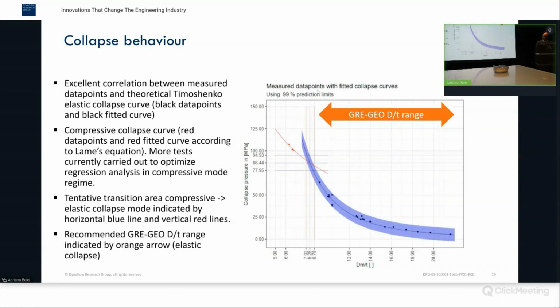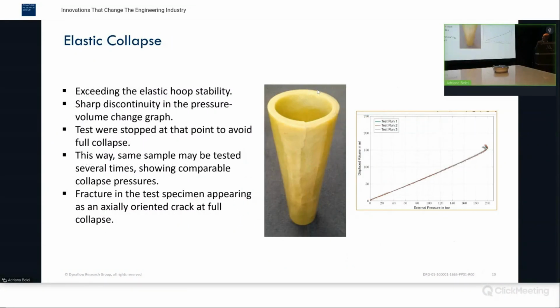We can show that on the next slide. At the right, you see a plot of displaced volume against the external pressure during an external collapse test. If you stop the test at the maximum level, around 200 in this case, unload the system and depressurize it again, you hardly see any difference in collapse pressure. That's also an indication that at these levels no damage will be introduced. In the picture of the pipe you see a typical axial failure. When you pressurize the pipe even further than indicated in the plot, you will get a typical axial crack.